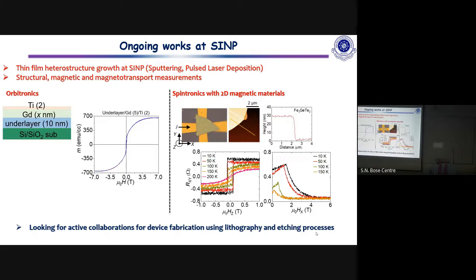But your RXY is increasing with temperature. Decreasing with increasing temperature. Which normally is not the case. No, the RXY decreases with increasing temperature. That is expected, because the magnetic signal will disappear above the ferromagnetic transition. This 200 is roughly the temperature. It behaves like rho XX. So you are saying it is because your magnetization is going down. Yes, magnetization is going down, so the magnetic phenomena weaken in the perpendicular direction.